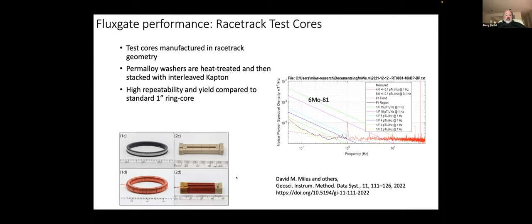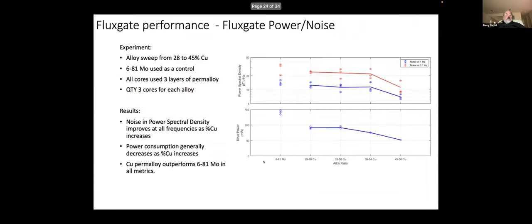Doing this with the 6% moly material produced a noise spectrum like this one, for example, and to compare that with the Intermagnet data standard, which has 10 picotesla per root hertz at 0.1 hertz here, this 6% moly material is now well below the requirements, the worst requirement for the Intermagnet standard. Again, this is because of both going to the thicker foils and going to the racetrack design. So as a reference point, we can now go from here on to looking at what the copper materials do.